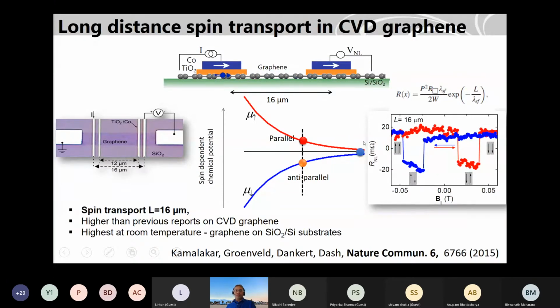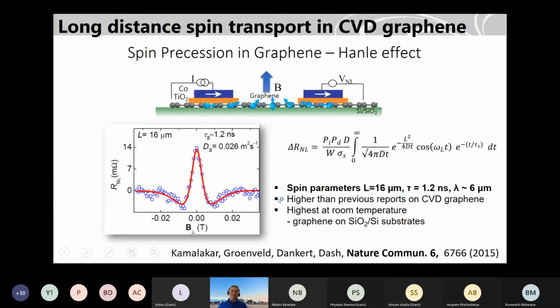And you know that we use CVD graphene. CVD graphene mobility is very low, around 2000 centimeters squared per volt second, and so the electron lifetime is very short, in femtoseconds, because it's a low mobility graphene. It should have lots of grain boundaries. You don't see them here; you have to use a transmission electron microscope to see the grain boundaries. But because this is so long, we should have grain boundaries. I'll come to that grain boundary picture.